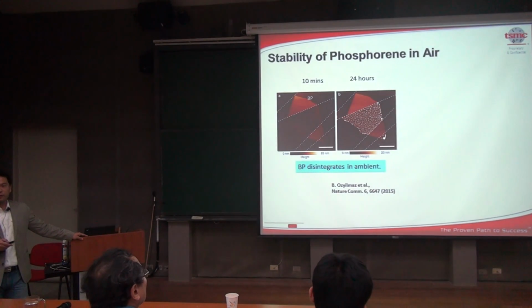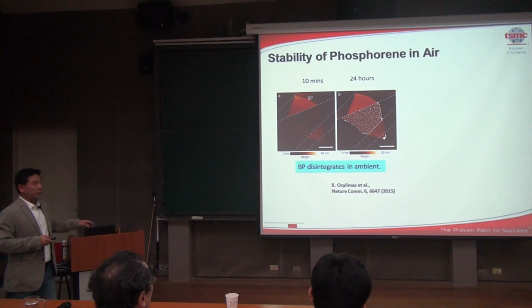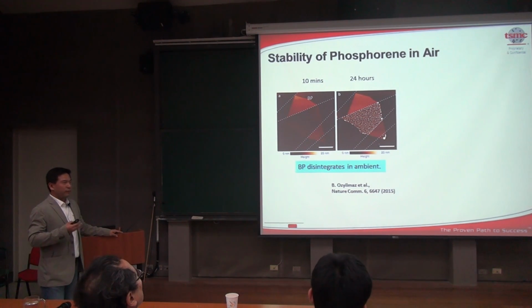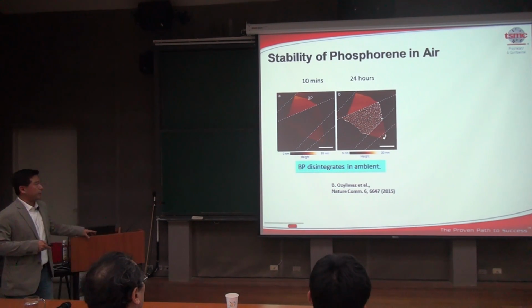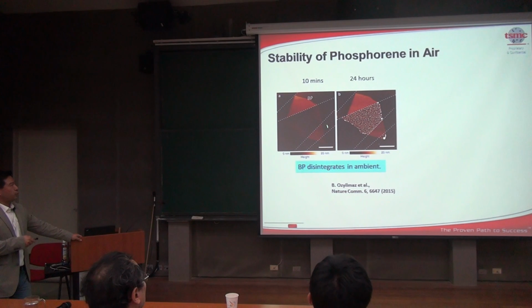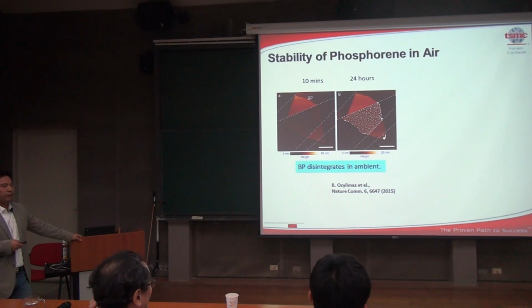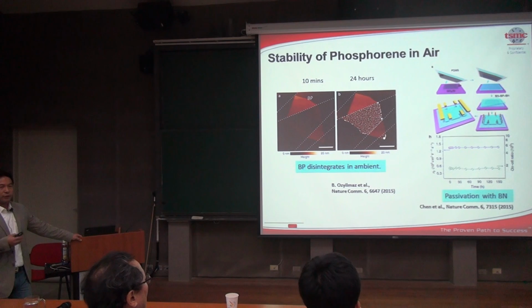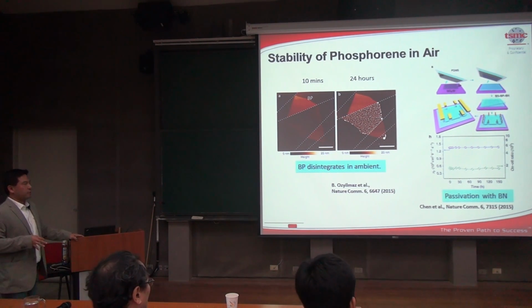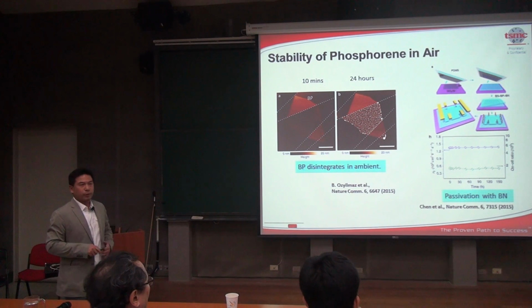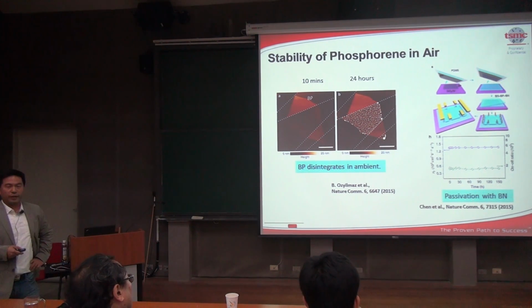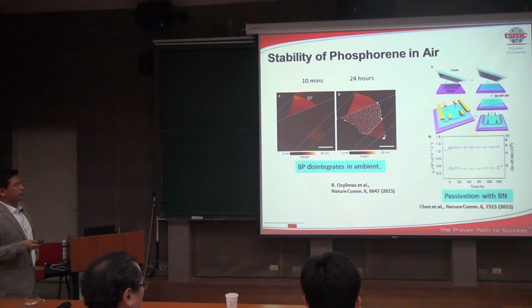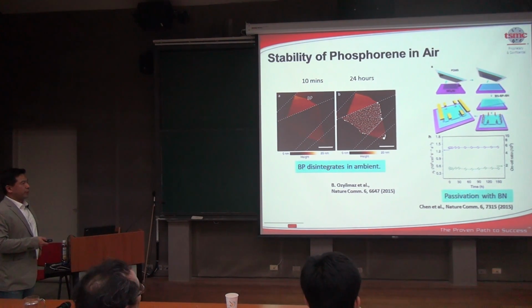One issue of black phosphorus, though, is its stability in air. It will start to oxidize and then vaporize in air if you do not passivate it. So this is a piece of black phosphorus with two parts covered by graphene, and this part exposed to air. And you can see within a day you start forming these bubbles, a very rough surface on the black phosphorus. So they disintegrate quickly, and you need to come up with some kind of passivation. But once you passivate, then they become quite stable, and you can make devices that are stable and can be repeatedly measured over days or even weeks.